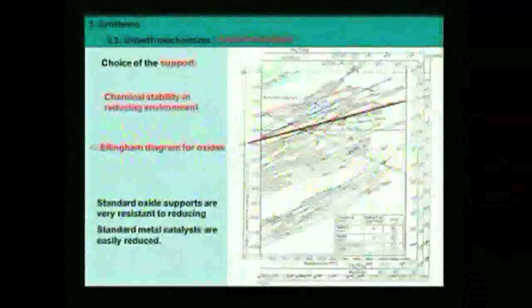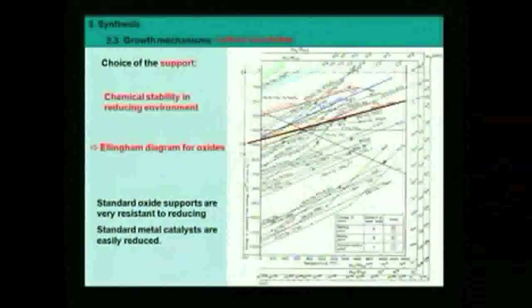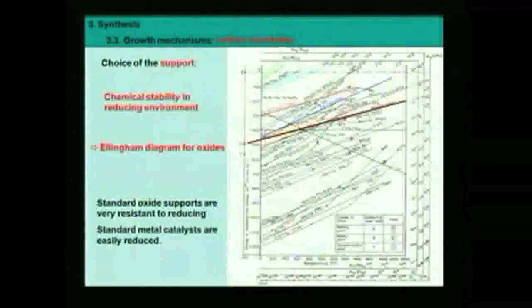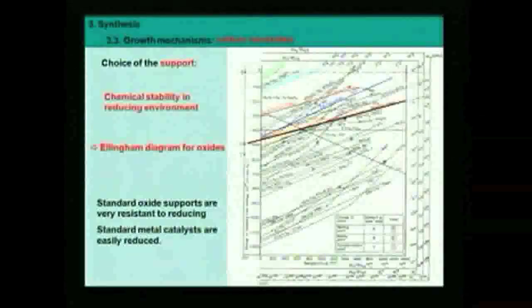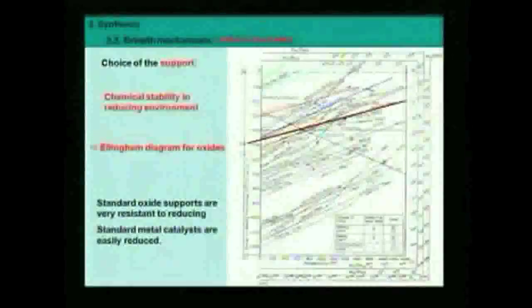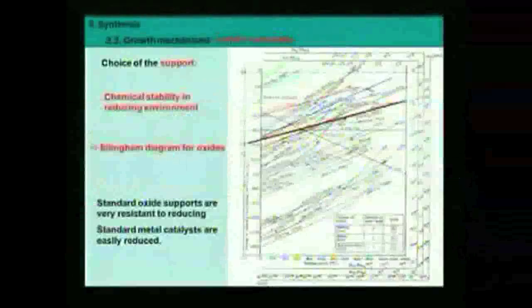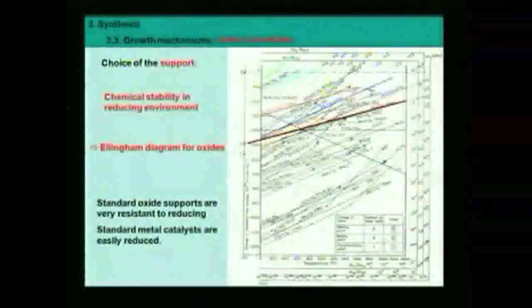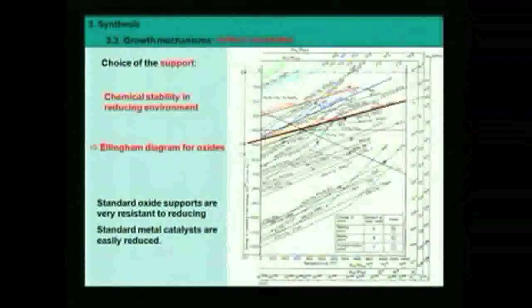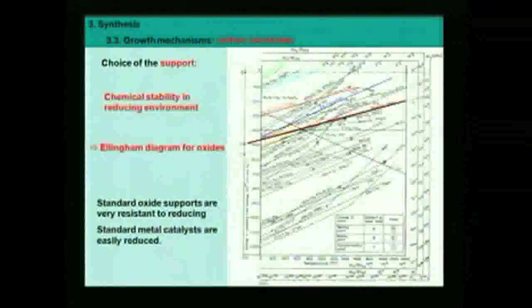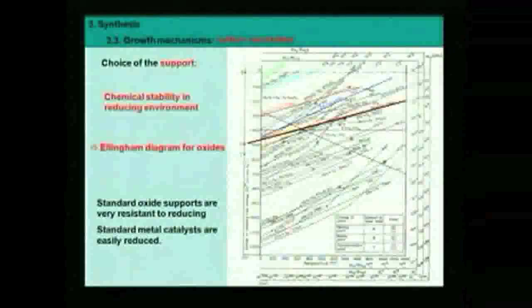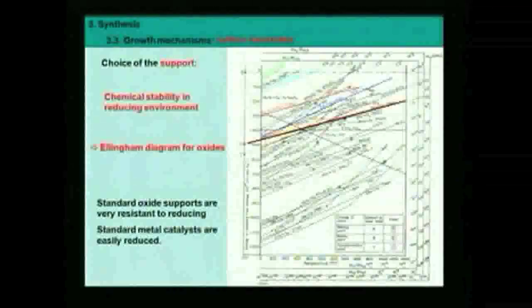So what does it mean? It means that if I shift the ratio of hydrogen to water, the line for hydrogen will not be this line anymore, but it will be shifted to another line which will intercept this value, for instance, and this value. Okay, I'm not going into the details of Ellingham diagrams. This is not the purpose of this course, but it's to tell you that these Ellingham diagrams are a very useful tool to know if you can do a special reaction, if the reaction will occur, if a special compound is stable or not stable in a given atmosphere, like a nitrogen atmosphere.